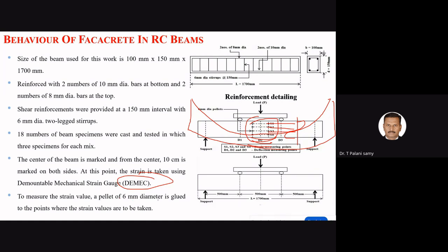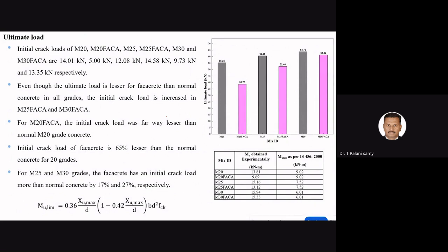Pellets of 6 mm diameter are glued on the points. We can measure the deflection also. Then you may remember this formula: Mu lim is equal to 0.36 (XU max/d) (1 minus 0.42 XU max/d) b d square fck. We compared these loads mathematically and experimentally with our code book recommendations.